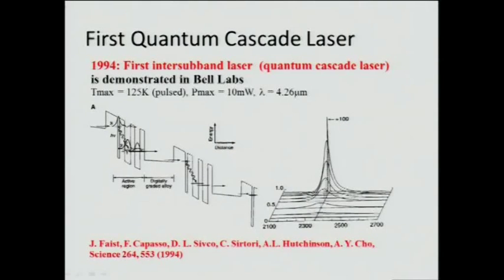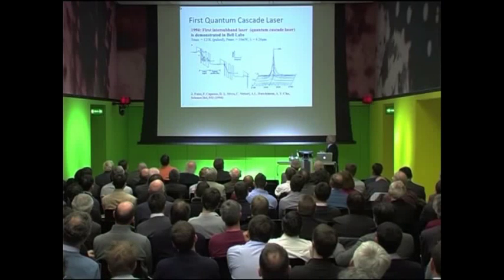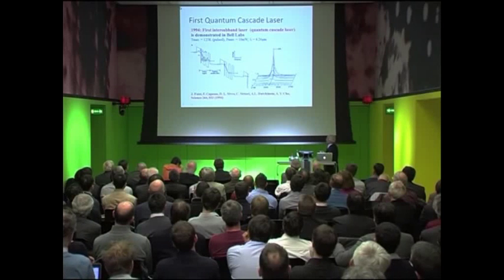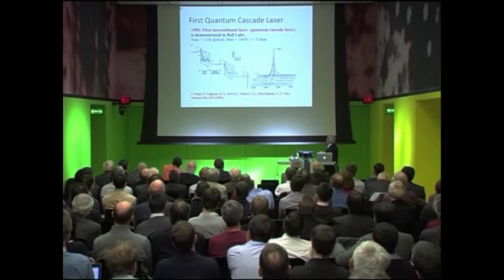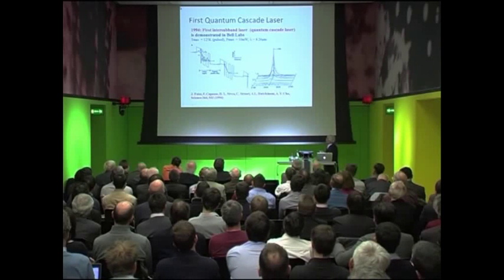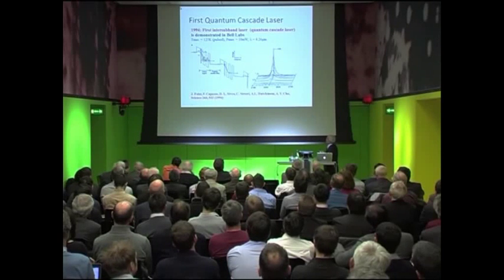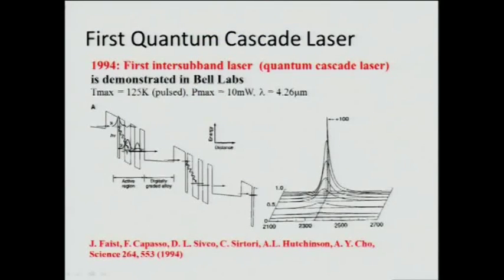That means the final state had to be 0. And the design of this quantum well adjacent to that is that the overlap of wave functions, therefore the optical phonon nearly 0 momentum transfer, and then compared with the transition, the relaxation time of the 3 to 2 is something in the order of 4.3 picoseconds, and then the final state here, the relaxation time is only about 0.6 picosecond, and that's what produced the population inversion and made the laser lase for the first time.